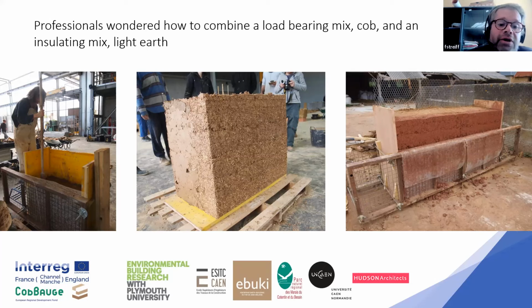And this first wall here in the middle finally dried pretty well, and no separation between the two layers, even if it was two different densities, two different materials. It seems to stick very well. So we tried to produce other samples with the soil studied in the lab. So the third wall you can see here on the slide, we used the soil studied in the lab to produce a few scale 1 samples and see if it works in the same way.